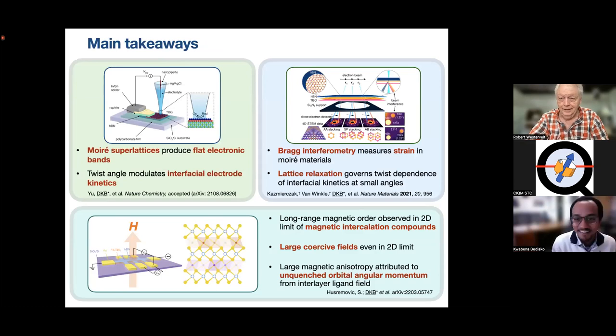Hi, Daniel. How can the droplet at the tip of the pipette distinguish bilayer from bulk graphite, since it's only adjacent to one surface? Yeah, great question. Well, even though it's only adjacent to one surface, there is a density of states at that surface, and this would be a question I happily flip back to you, Daniel, since you're the theorist. But the density of states at that surface must be less for the bilayer than the bulk graphite, so that the overall electrochemical process is still sensitive to the number of layers.